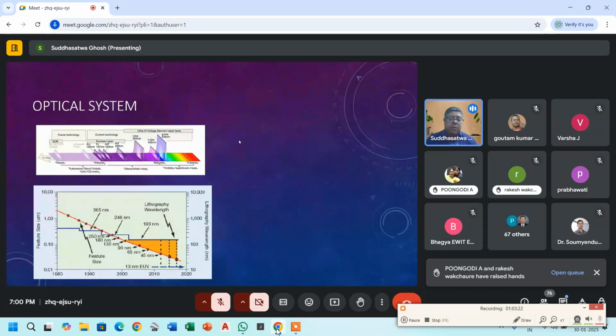For example, what you see here is that in photolithography systems, we typically use ultraviolet rays because they have a very small wavelength compared to visible rays, and also it depends on the photosensitivity of the photoresist, which reacts to ultraviolet rays. But as we wanted to achieve finer and finer resolution, the industry had to move from longer wavelength ultraviolet to much shorter wavelength ultraviolet. It started with 436 nanometers, then 405 nanometers, then 365 nanometers, and then 248 nanometers wavelengths. So basically, the optical wavelength played a very critical role as we moved from the larger feature size to the smaller feature size.